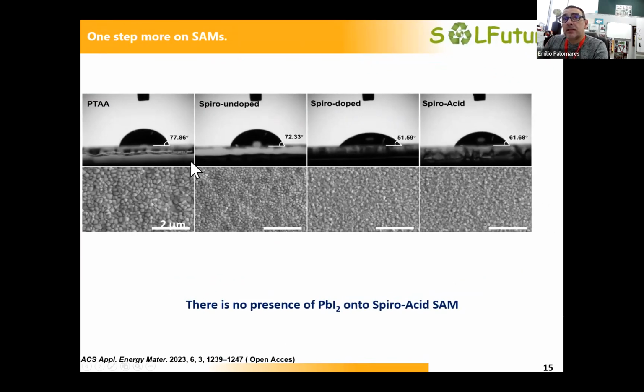One thing that we observe is that, as I was saying, to deposit these organic materials on top of the perovskite, you have different angles. And as you can see, the highest angle is the PTAA, and that makes it very challenging to get good efficiencies when using PTAA on perovskite, which I believe will be an issue when you want to go to modules.